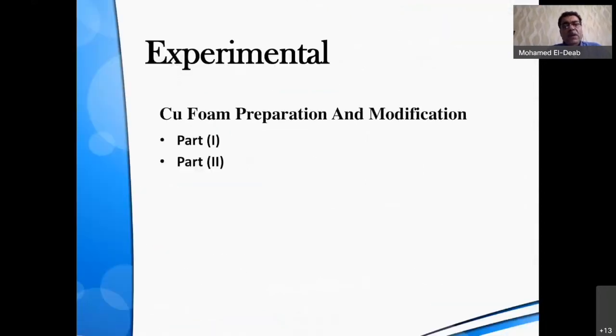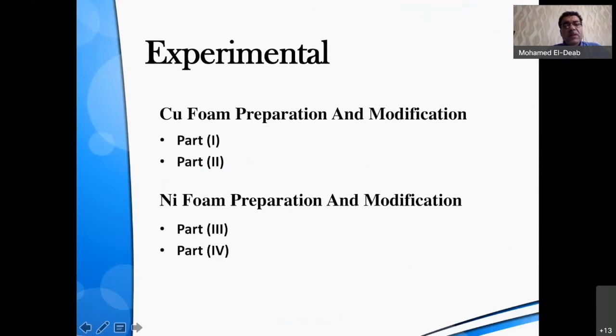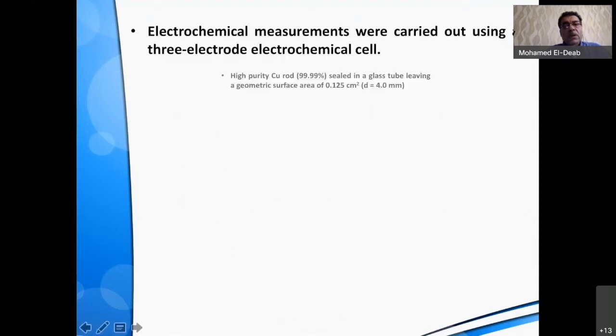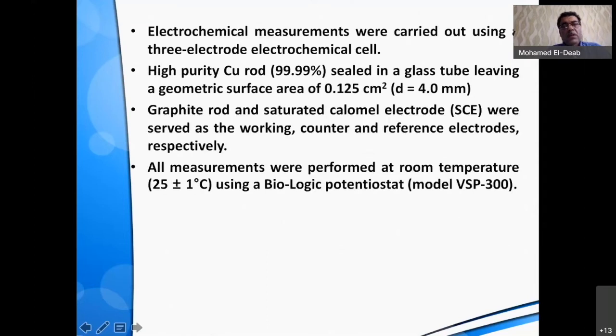As for the experimental part, we prepared copper foam atop copper foil in the presence of different additives, and we also prepared nickel foam on copper foil, also in the presence of different additives. I'm going to present only a little part of this presentation. This study has been published in the Journal of the Electrochemical Society, Electrochimica Acta, International Journal of Hydrogen Energy, Renewable Energy journal, and also RSC Advances. You can see it from my list of publications.